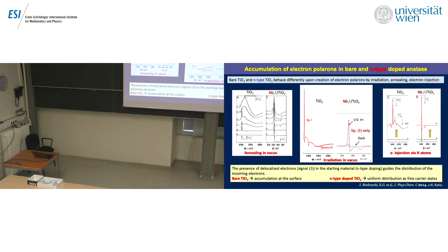Here is the niobium enriched. So there is an initial spectrum because niobium is in the system, but all the other trapped electrons have the same feature as the initial one. And so there is this big difference. If you inject hydrogen atoms, it's not difficult to do that, okay? You have the 2 signals with normal titanium and 1 signal only. Look, this is beautiful because it's the same signal that grows in intensity. So the message is that in this case, you get a uniform distribution of the free carrier state. And this is not unimportant for people working in applications in photovoltaics, etc.